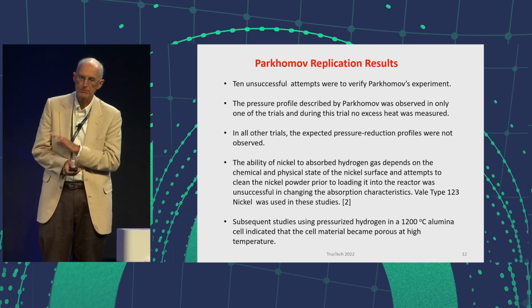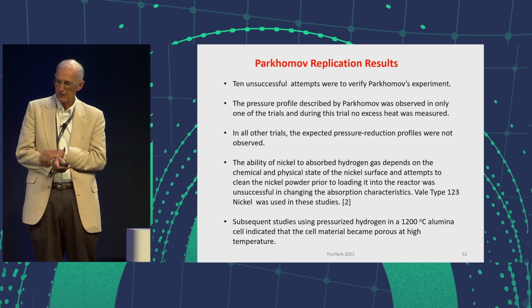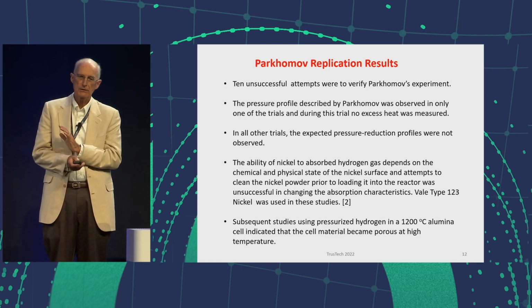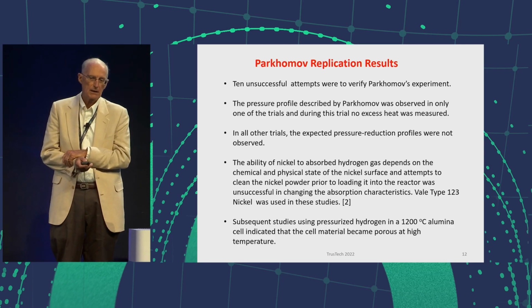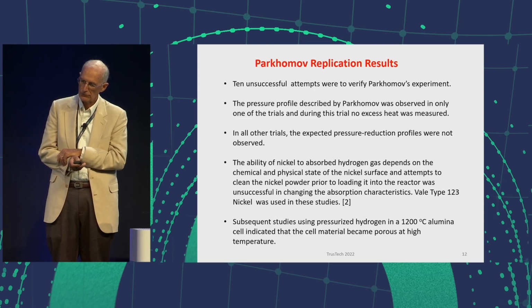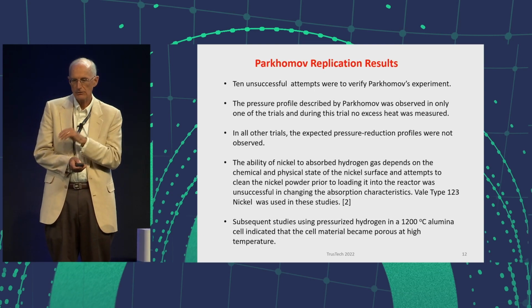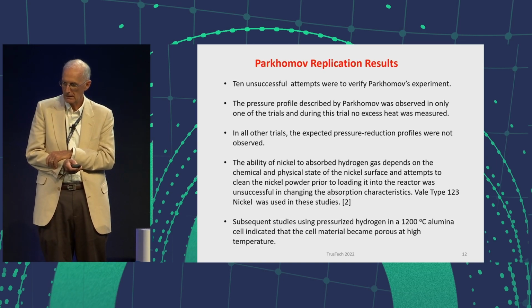The ability of nickel to absorb hydrogen depends on its chemical and physical surface. And I chose a type of nickel, which is Vale 123, that electron micrographs made look very similar to the nickel that he used. But cleaning this material didn't have an effect on the outcomes of the results.